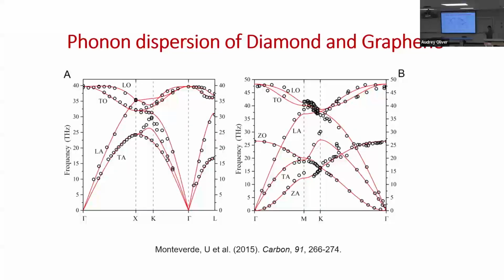We can also look into lattice dynamics. So there are a few methods. One of them is density functional perturbation theory. Based on that, we can calculate those vibrational properties, right? This is frequency, and these are K points, right? So you can see acoustic and optical, right? These lines are calculated, and the circles are experimental. So it perfectly matches with the experiment.